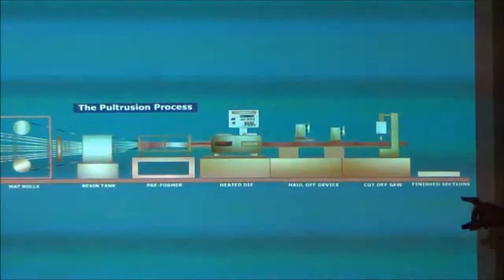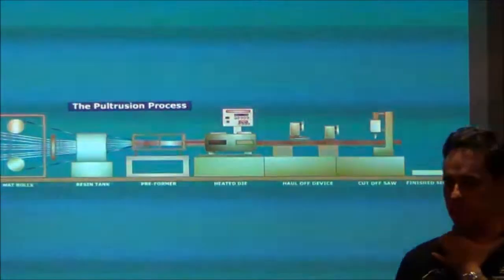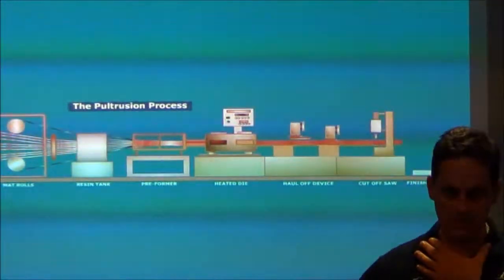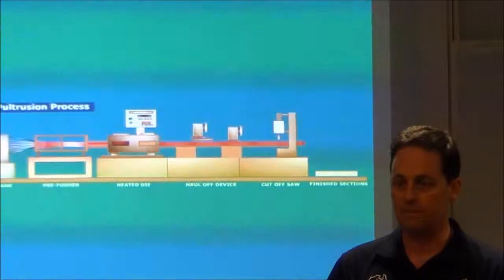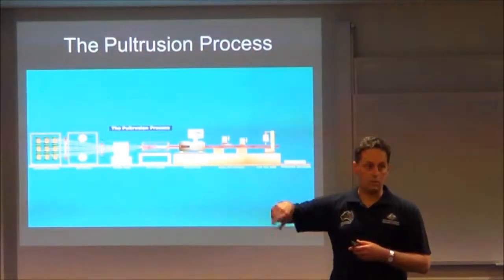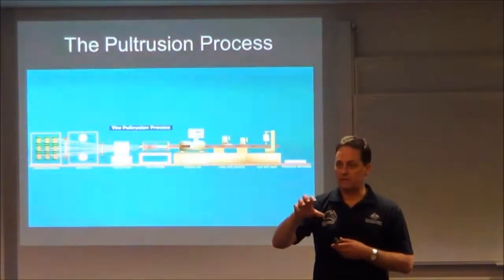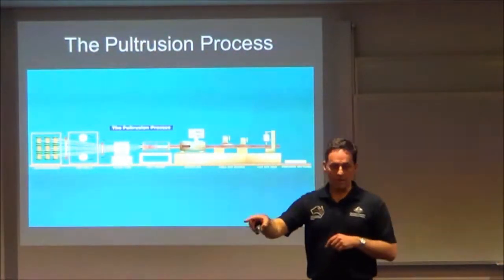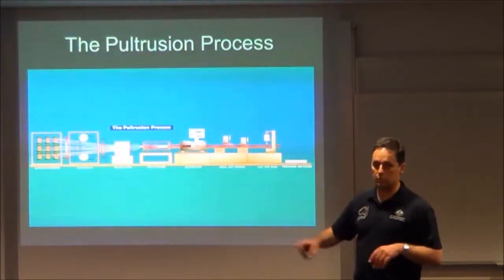This particular process will produce, if you wanted to, a dowel. So that smooth bar that's going around now, it produces that. And in the pultrusion process, it produces that, and then it's cut. The groove is cut post-process. So what you've got is a groove which is bound in exactly the same way as the rest of the fibres are bound to the bar, as opposed to a sand-covered bar, which goes through a process after this, whilst the bar is still hot, while the resin is still hot, and it's bonded externally. But it allows for complete gripping of the concrete matrix to the bar. So that's the V-rod. Pultron can make a sand-covered bar, but it's not the normal application. They won't do that normally. And most of the stuff that you see here, this application will produce a straight bar.